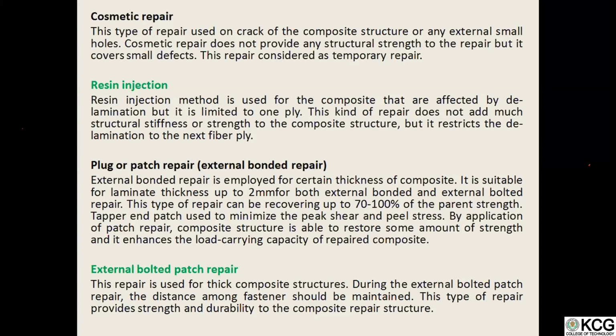The other method is external bonded repair. This method is a temporary method. It is not a permanent method, because we just need to make the surface preparation and paste one more bond layer. The bond is nothing but the same architecture panel that is used for the parent material. This kind of repair is able to recover 70 to 100% of the strength of the parent laminate if we do it in an optimized manner. We need to make the surface very clean and paste the patch very neatly. After doing that, it will recover up to 70 to 100%.